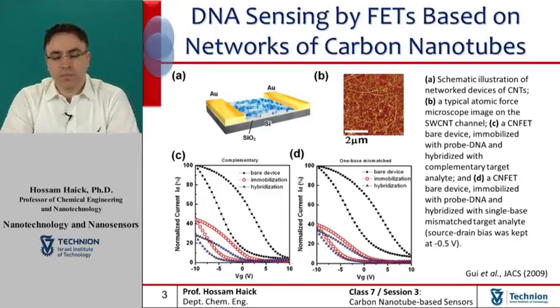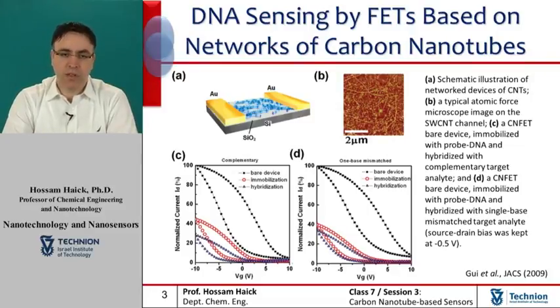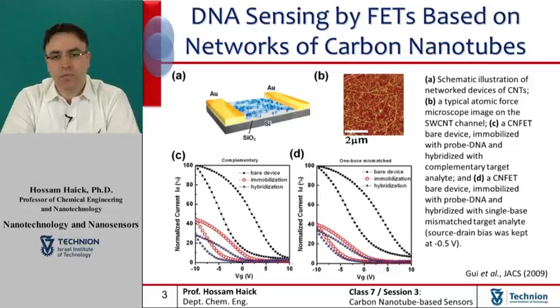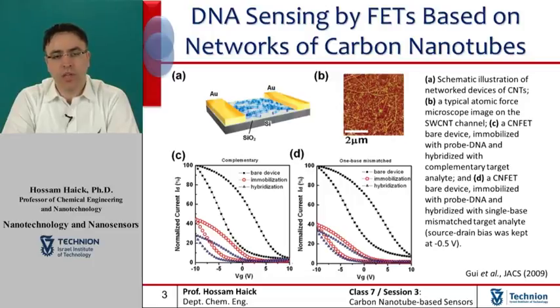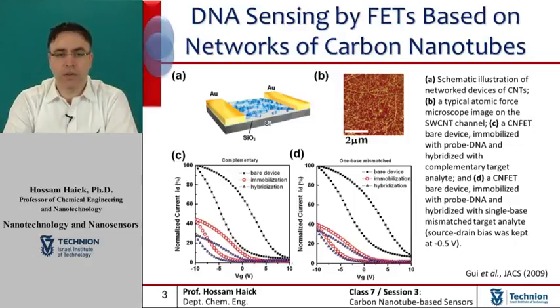The device is immersed in synthetic oligonucleotide buffer for a period of 16 to 24 hours. A standard rinsing was performed to remove the weakly bound DNA molecules. For hybridization experiments, complementary target analytes were pipetted into the immobilized device and allowed to react for approximately one hour. Figure C shows the typical gate voltage dependence of the normalized drain current for the device immobilized with capture-probe DNA and hybridized with complementary target analytes.